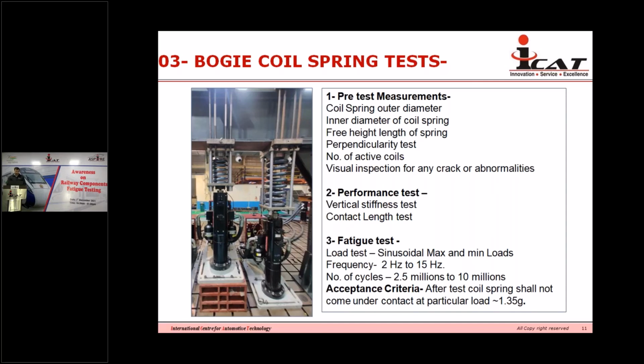And then after the fatigue test, we need to check the vertical stiffness, or contact length test. In the fatigue test, we apply the load in terms of sinusoidal waves, maximum and minimum loads, with some mean load, or you can say some static loads, which is coming on the spring. And this frequency can vary from 2 to 15 hertz or more than that, but considering that there is no heating of the springs.